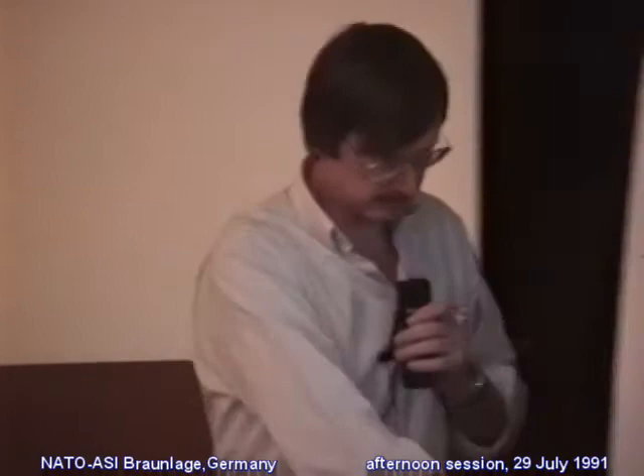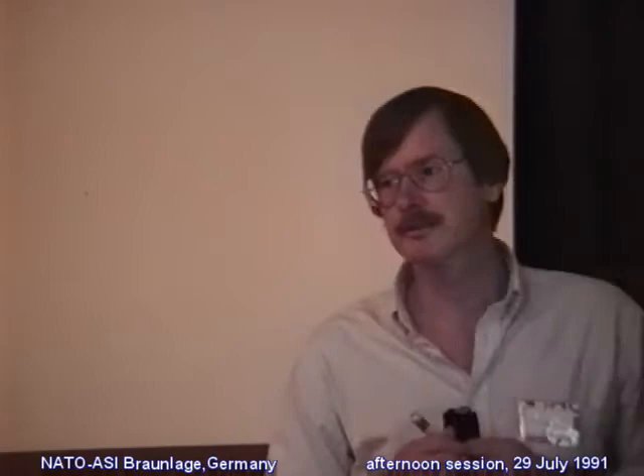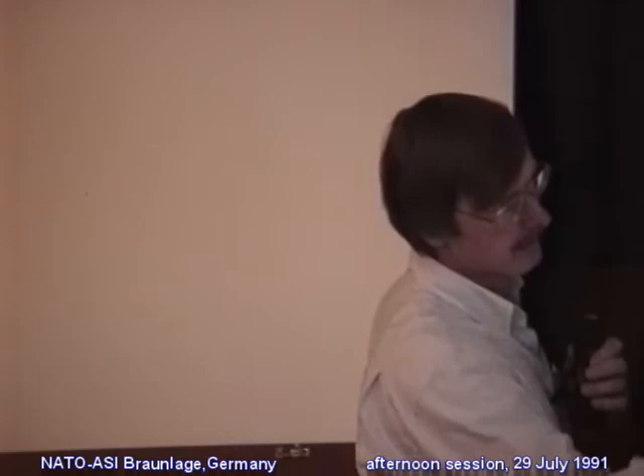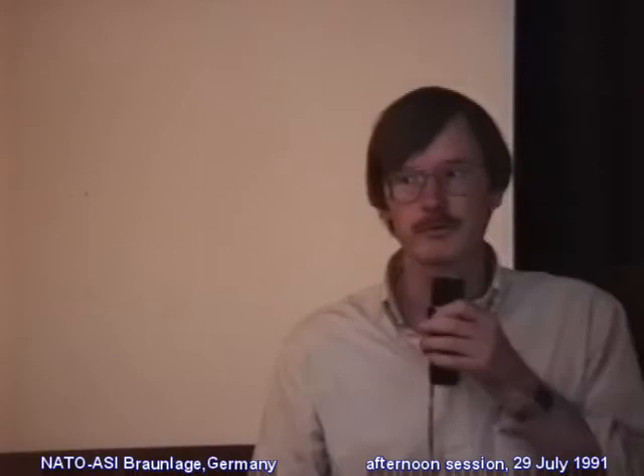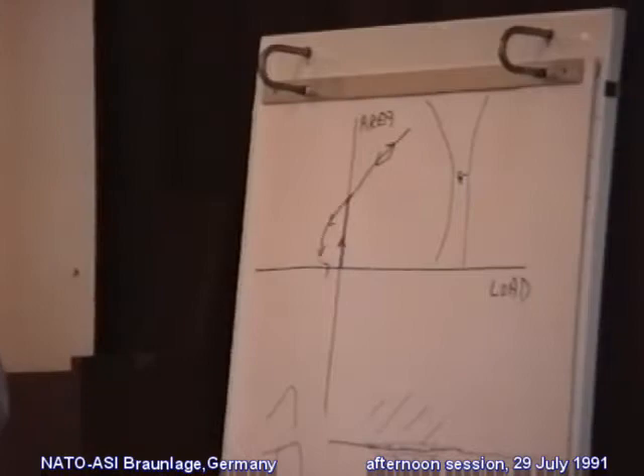This is really plastic failure, so that's void coalescence. If you pull a piece of plasticine and you get necking, final fracture occurs because the continuous phase pulls away from the particulate phase, and then you get void coalescence across the cross section. So, section rupture.